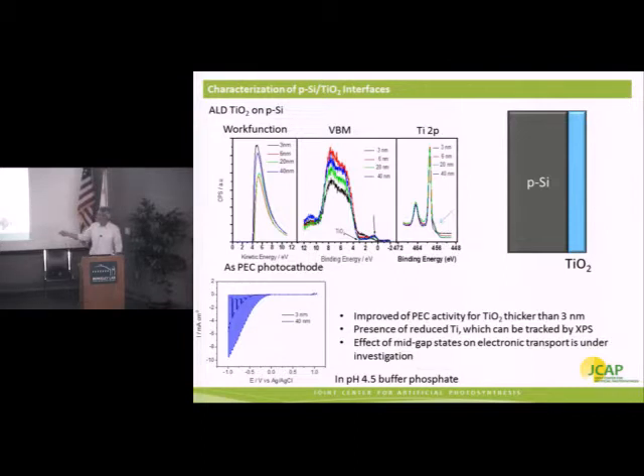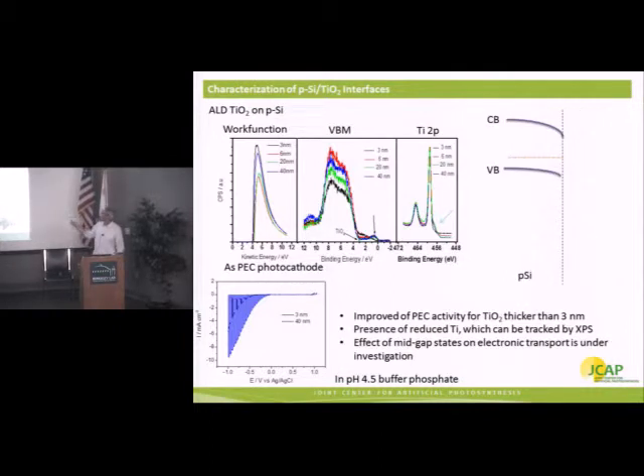If we combine this observation with our results from photoelectron spectroscopy, we can construct a bit of a band diagram where we have the p-type silicon with a downward band bending. And what we ultimately end up with is a TiO2 layer with a conduction band that lies lower than the conduction band of silicon. So we can directly inject charge into the conduction band of this TiO2. This is a perfect layer for separating the semiconductor from the electrolyte. This can be used for interface passivation if we use the right procedure to deposit the TiO2, as well as corrosion protection.